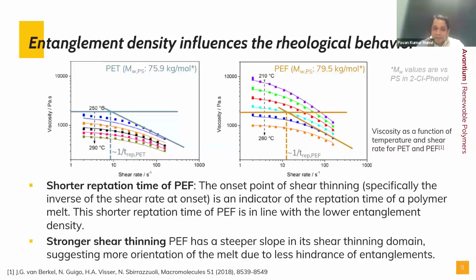What is the impact in the processing of textiles, like in fiber making? That means if there is a steeper slope in the shear thinning, then it is possible to get a higher orientation in case of PEF than PET, and this orientation is directly connected to the mechanical properties. Mechanical properties means the tenacity, the modulus, and so on. So starting from the basics of PEF rheology, reptation time, and lower chain entanglement density, and then shear thinning behavior, we understood how we can use this phenomenon in getting better properties in fibers and in textiles.